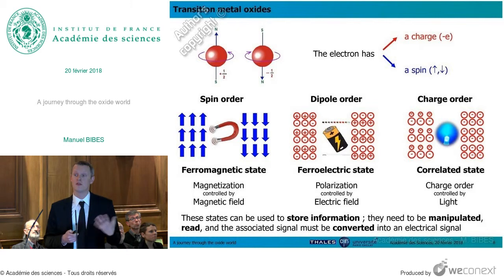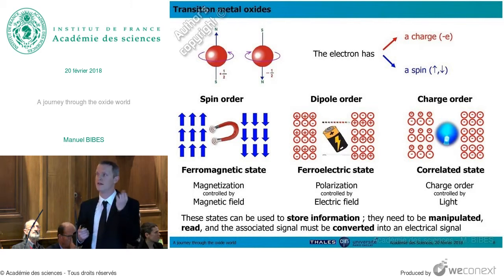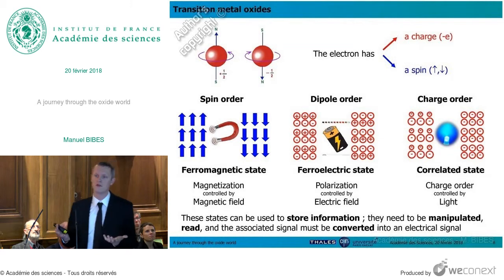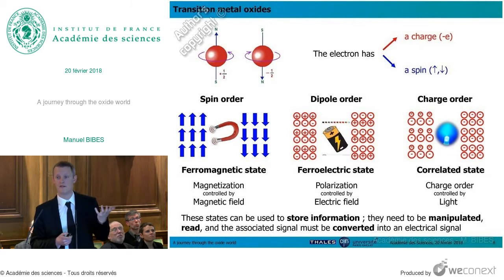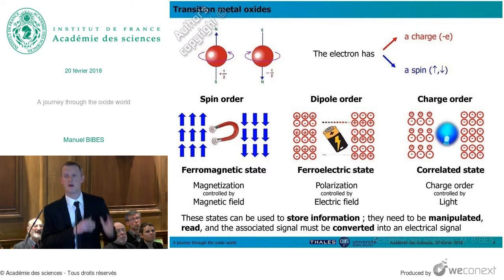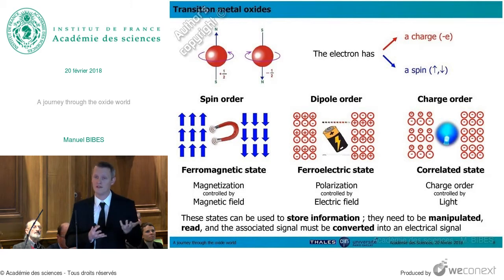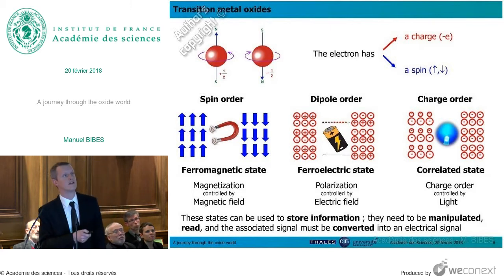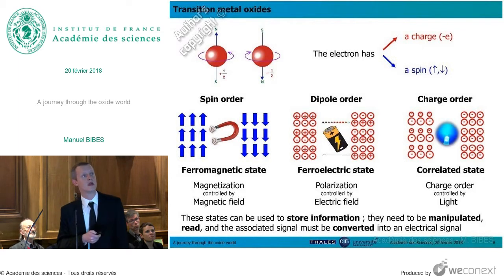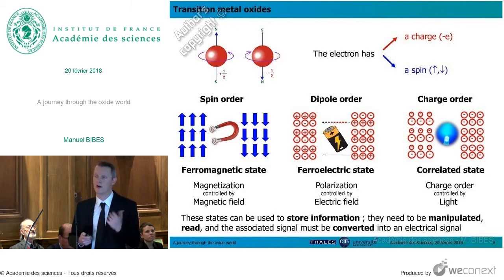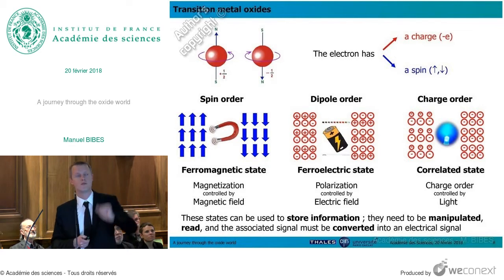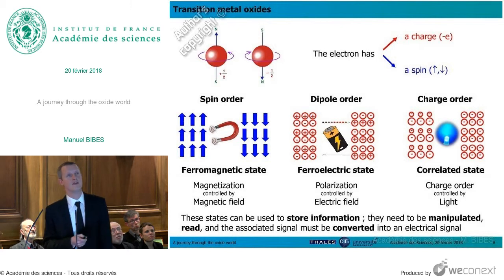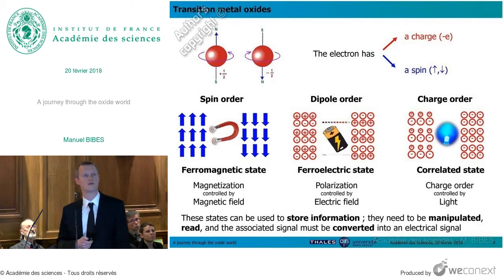What's interesting is that you can manipulate these states by applying an external stimulus. For instance, if you apply a magnetic field, you can switch the direction of all these spins. Taken together, we call them the magnetization. And so we can reverse the magnetization by applying a magnetic field. Equivalently, for the ferroelectrics, all these dipoles together are called the polarization. And we can reverse the polarization by applying an electric field. And this charge order, if we apply light, for instance, we can destroy it. So we can control this charge order by light.